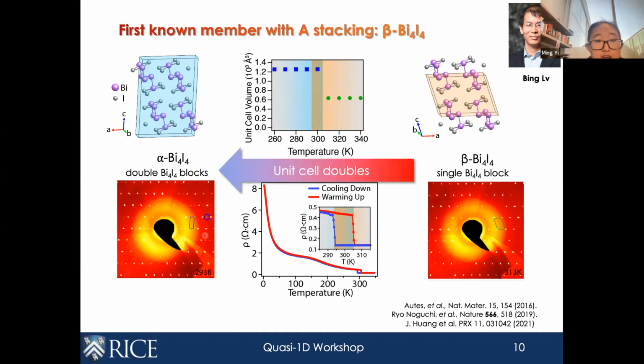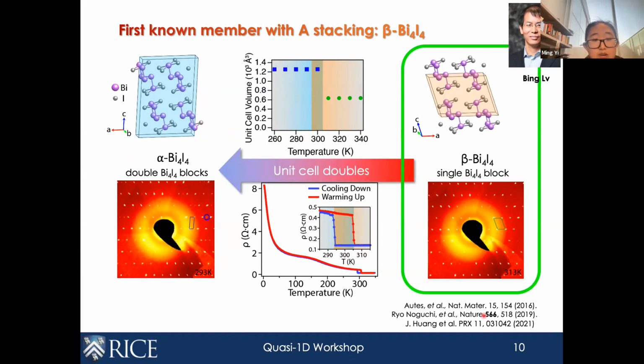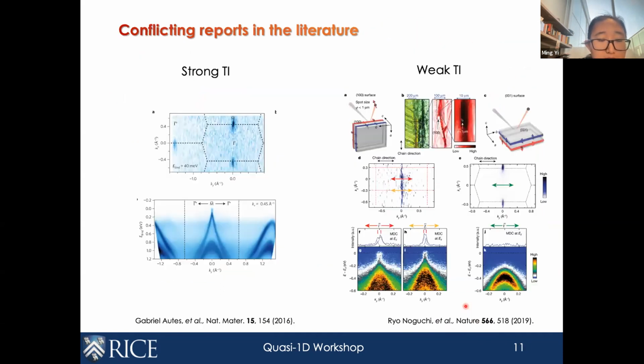But let's first talk about the simplest scenario of a single block, single layer phase, the beta phase, and what does ARPES observe as a topological state? So we look at the ARPES results on this, and there's been a controversy in the literature regarding bismuth iodide, with one paper reporting a strong TI phase, and then this is Takeshi's very nice paper showing that it's a weak TI using nano ARPES.